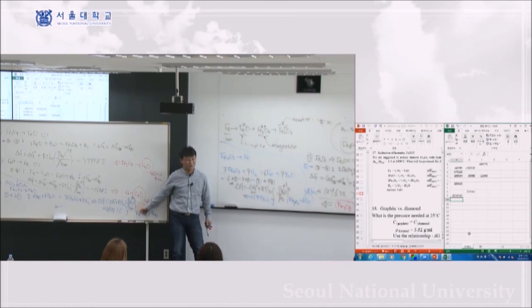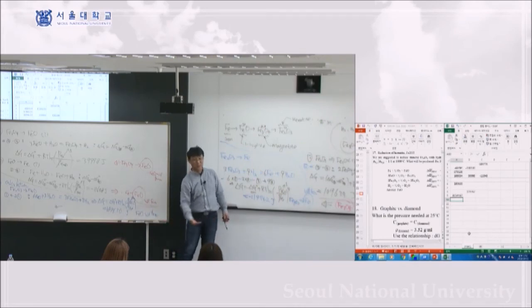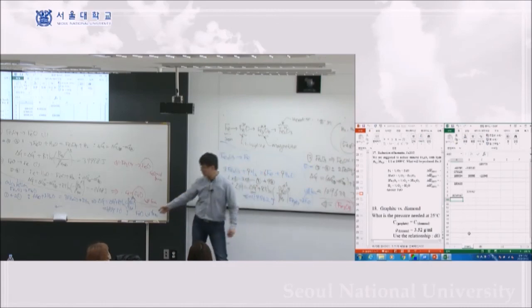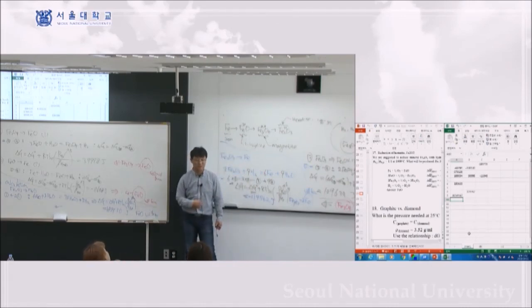No. You should not do that. That energy difference doesn't really tell you whether this is stable or not. It's a bit dangerous. Okay? We are just doing the transient calculation. It's not the final equilibrium state. If it's the final equilibrium state, then yes, the lowest energy state is the one we want to produce. But we don't know whether this is the lowest energy state. Now we are just starting the chemical reaction. We are still in the middle of the chemical reaction. So we cannot really say this is the most stable state according to the energy itself.